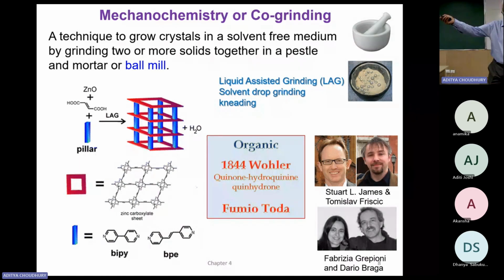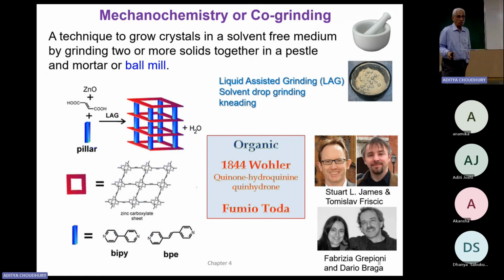Exactly the same thing. I went to a few labs. Whenever I went and started asking the same question, they say, in the case of either ball mill or pestle and mortar, when you grind them, that generates a lot of heat. In the case of pestle and mortar, maybe a few hundred degrees. You don't realize locally. And ball mill, maybe several. According to them, it's several, which I don't believe. But at least several hundreds when you do ball milling, in local spots.